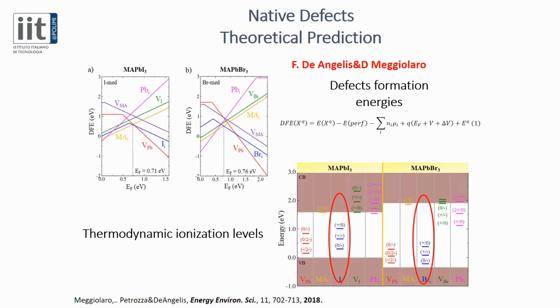These are data from a colleague of mine, the group of Filippo De Angelis in Perugia. So when you want to understand which type of defect we have in a material and how important they can be on the performance of the semiconductor, the first thing you need to know is the defect formation energy. The other important thing is the thermodynamic ionization levels of defects. This means, if you have a high density of defects, whether these defects are actually introducing a carrier trap state within the band gap of the semiconductor. In this case, they would be detrimental. Otherwise, they may not affect the property of the semiconductor.